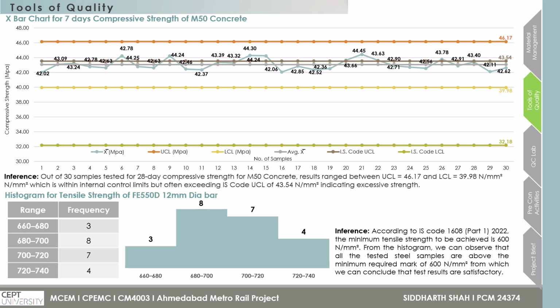Next, the X bar chart for compressive strength of M50 concrete. We got this data from the site itself, and out of 30 samples tested for 28-day compressive strength for M50 concrete, results range between UCL 46.17 and LCL 39.98, which is within the internal control limits, but it exceeds the IS code UCL limit of 43.54 Newton per mm square, indicating excessive strength.